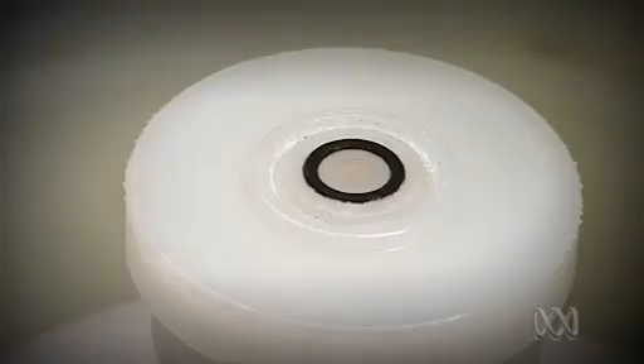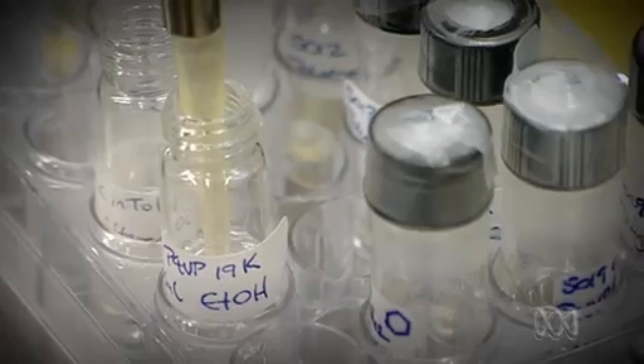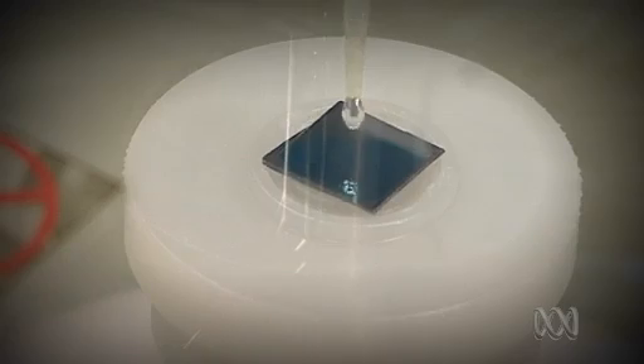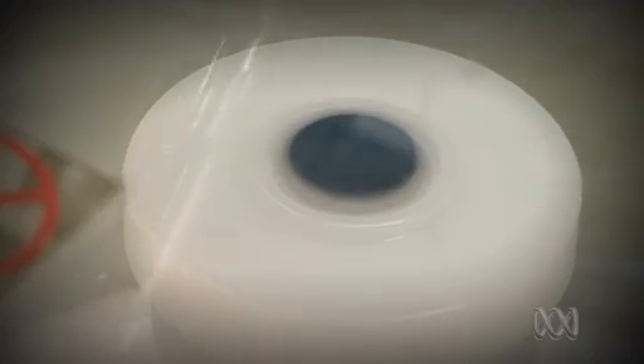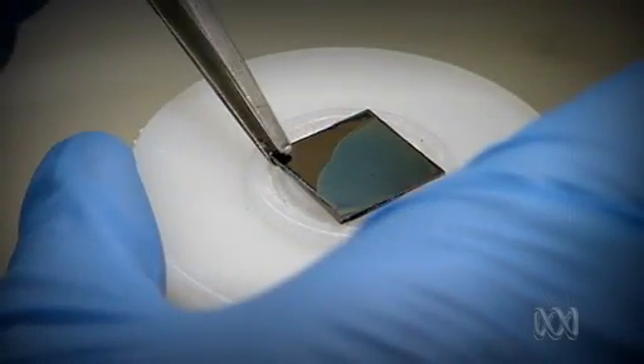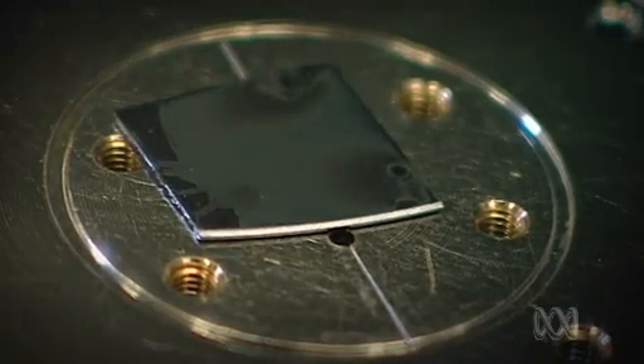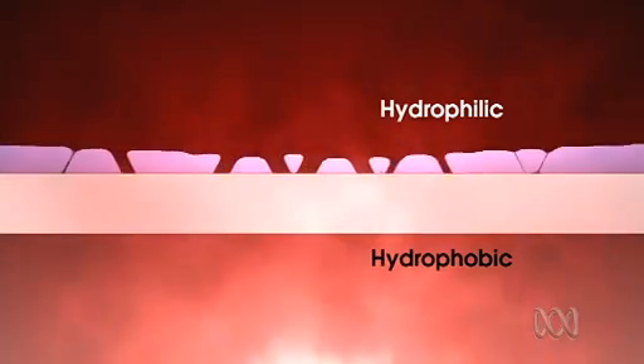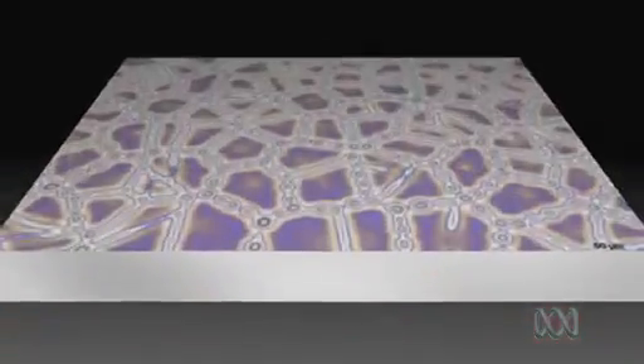So that's another very interesting example where nature really optimizes surface properties. And I've been working for a long time in thin film de-wetting, so that immediately struck me as a very easy way to produce hydrophilic bumps on a hydrophobic background. The process is surprisingly simple. Two polymers are spin-coated onto a substrate to create a double layer. When heated, the top unstable polymer breaks apart, leaving a surface that looks like this.